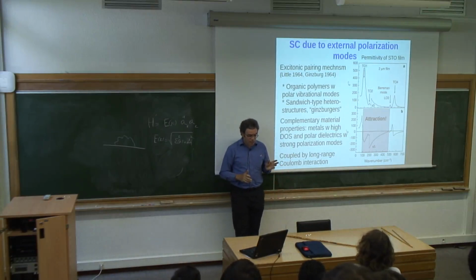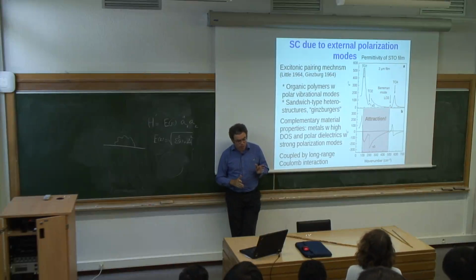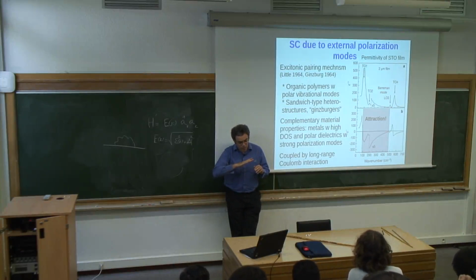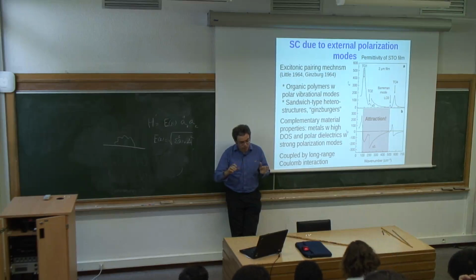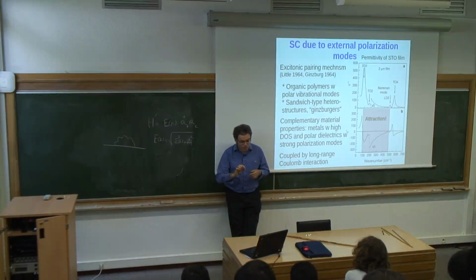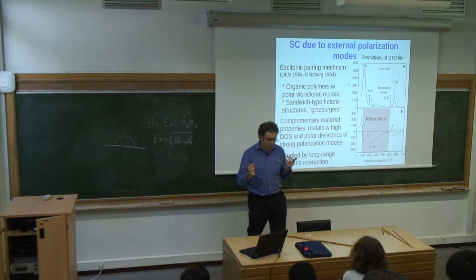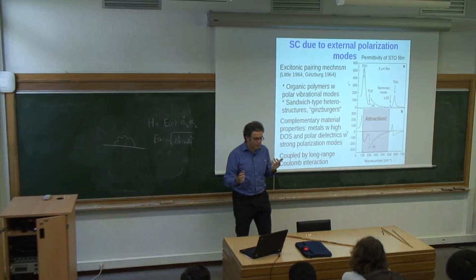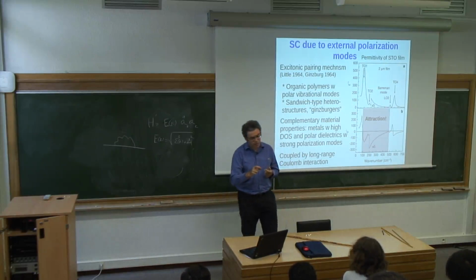And so that research continued for a long time, and there have been various mechanisms invented along these lines. Experimentally it didn't go anywhere because at the time all superconducting films that people could create, even if they thought about them as being quasi-two-dimensional, were actually too thick for this effect to play a role. Even if you think about a niobium film, niobium intrinsically has a TC of order 12 Kelvin, which is respectable, and it's very easy to grow a niobium film which is very, very thin, but very, very thin means something like 2 nanometers, and 2 nanometers is still larger than the screening length in niobium.